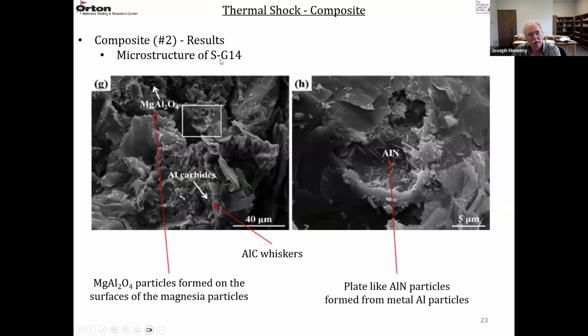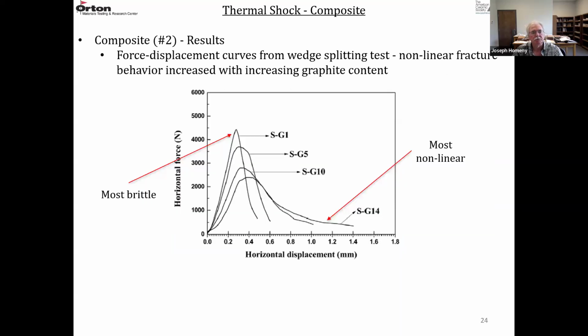And then the last one, SG14, again, they're showing areas of spinel. Here's an aluminum carbide area. It's pretty much in whisker form, aluminum carbide whisker. So again, the spinel is forming on magnesia particles. And here's some more aluminum nitride. This area here is blown up here. So you see these plate-like structures of aluminum nitride. So these micrographs are just pointing out the minor phases that are present.